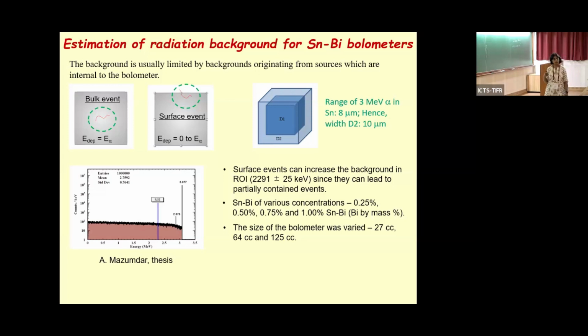So in fact, many of the experiments like CUORE have spent a lot of effort in having the pure crystal, getting rid of the alpha impurities. And they have further gone to things like scintillating bolometers, which I didn't talk about, like Lucifer, because they are then looking at both. When you're looking at temperature rise, you're looking at a phonon signal. If you look at the scintillator light, then you get a photon signal, and that is different for alphas and electrons. So by a combination of phonon-photon signal, you can improve the background further.